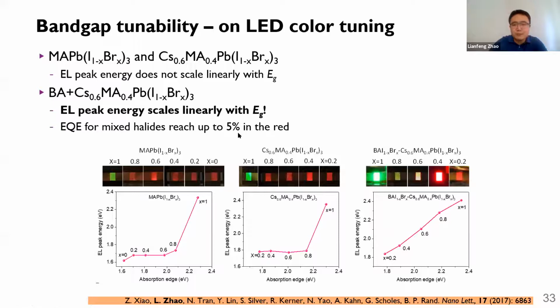So using this strategy, we were able to demonstrate wavelength tunable perovskite LEDs. As you can see here, the light emission energy is linearly tuned with the absorption edge. But for the control samples, the emission can only be green or red, corresponding to the iodide-rich and the bromide-rich light emission.